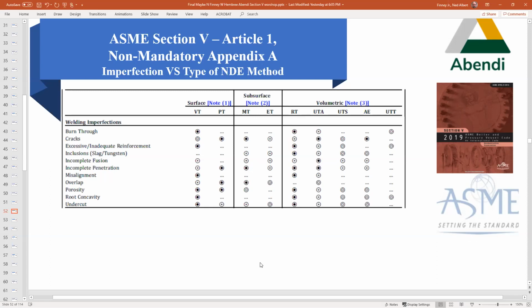I'll note that OD undercut associated with welding for the power piping indicates that at the toe of the weld, the acceptance is determined by mechanical means, not just by it showing up on a radiograph, or by saying, okay, I can identify that off of a full V bounce with ultrasonics. It says mechanical means for undercut. You can see it visually, and yes, you can see it in radiography. But the actual disposition of that, according to the power piping, unless they've changed it recently, but I've worked with the last edition, is to be dispositioned via mechanical means, which measures it. Next slide.